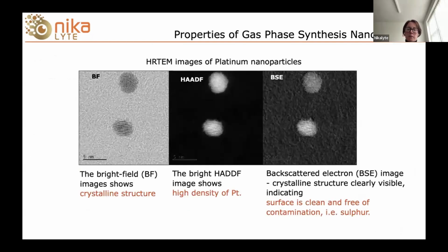I mentioned that the nanoparticles are ultra pure and there's no surfactants. We actually have evidence for how clean our materials are, and these high resolution TEM images of platinum nanoparticles demonstrate that very nicely. So these nanoparticles have been imaged with 3 different detectors, a bright field detector here on the left, a high angle annular dark field (HAADF) detector in the middle, and a backscattered electron detector on the right. And what they show is the same nanoparticles, first in bright field, which effectively shows us the crystal structure of the bulk. So you can see again, those lovely atomic planes in the platinum nanoparticle.